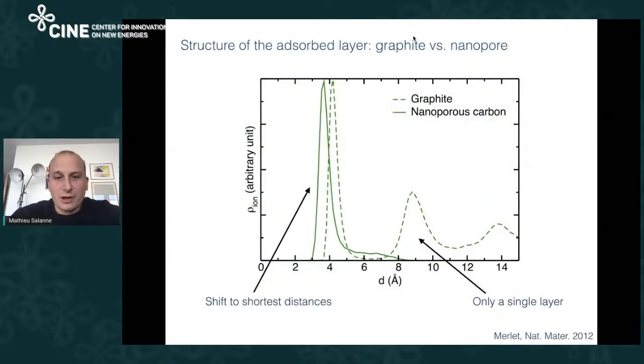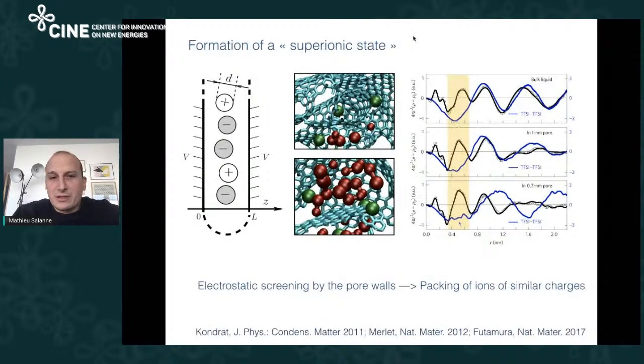Then we try to go further into understanding what are the structures that are the origin of this increase of carbon charge. And in fact, at the same time as us, there was the group of Kornyshev who proposed, based on a theoretical study, that due to the confinement, you start to form what they called a superionic state. In a normal ionic liquid, every anion will be surrounded by cations and vice versa because of the strong Coulomb attraction, and also because you have a strong Coulomb repulsion between anions and between cations. But Kornyshev's model showed that due to the screening of the electrostatic interaction, because you have strong electric fields due to the carbon, you start to have this kind of packing where you can arrange several ions of the same sign to be close by inside the pores.